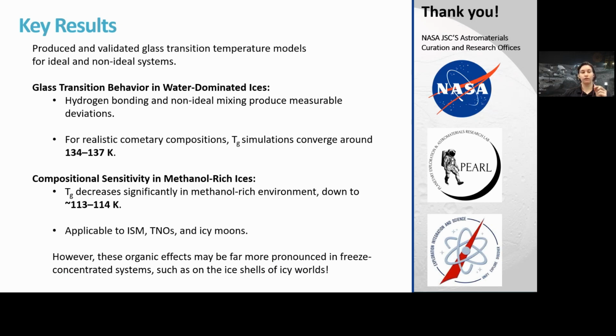Now to conclude. So we've produced and validated a glass transition model for both ideal and non-ideal systems, incorporating realistic abundances for cometary and inferred lunar compositions, where those values are mostly going to converge around, again, 134 to maybe 137 Kelvin, such that the organics have a fairly minor contribution. However, if methanol is significantly increased, those can be much lower. Big caveat that this is for the bulk glass transition, assuming one homogeneous system that then undergoes a phase transition. But it may become much more pronounced if you have some kind of fractionation. Thank you.